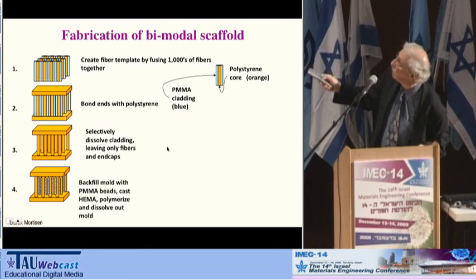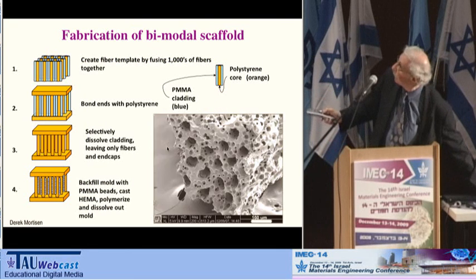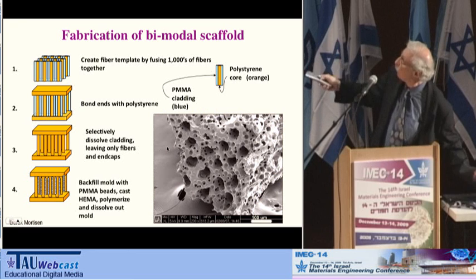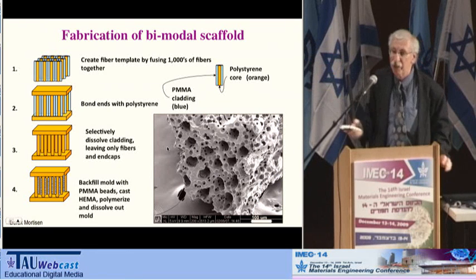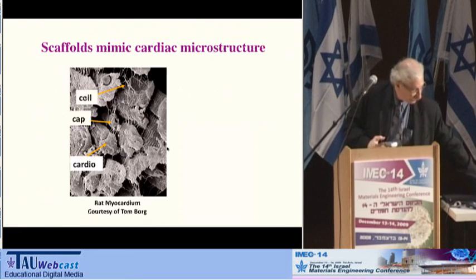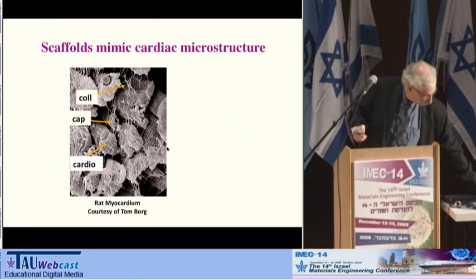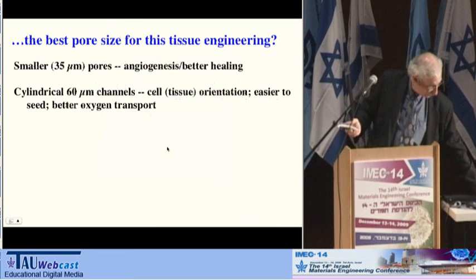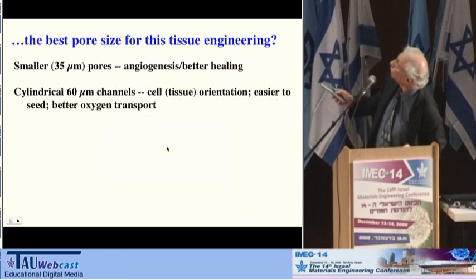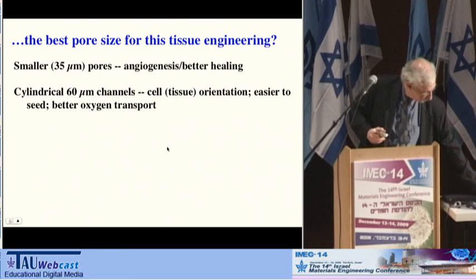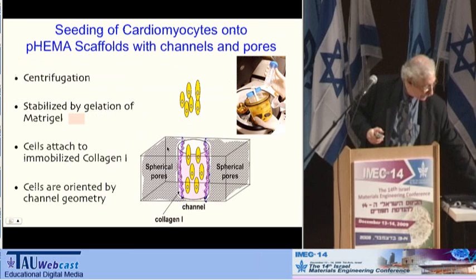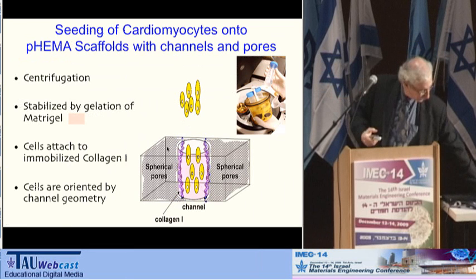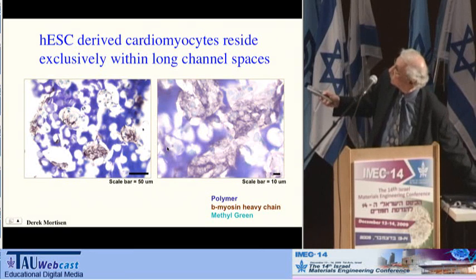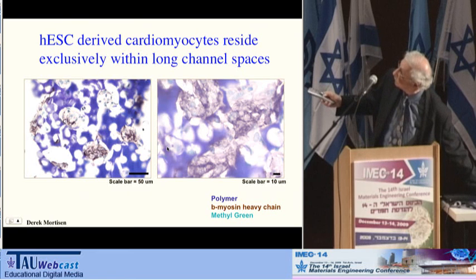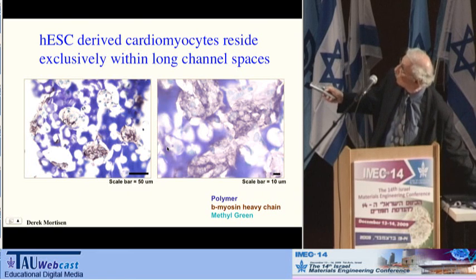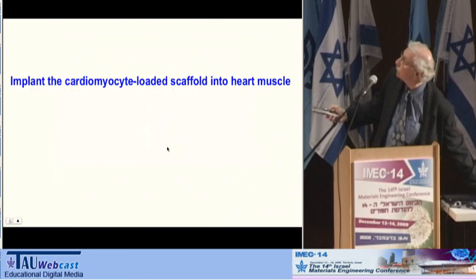We've developed another templating process using optical fibers, actually, to develop a material with long channels for cells and the sphere templated structure for angiogenesis. And this just compares that material to heart muscle. And let's see here. Let's skip this again for lack of time. And then we're seeding cells in, and we found that these heart cells populate these long channels. You can see them in the long channels.